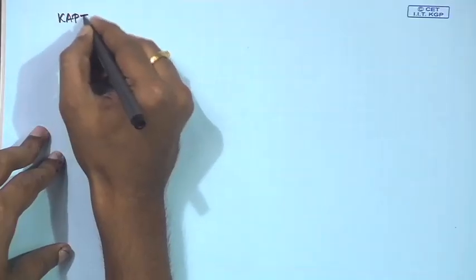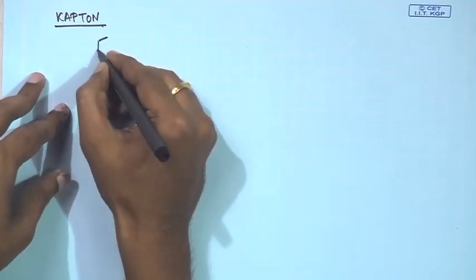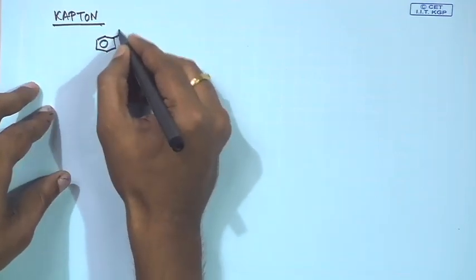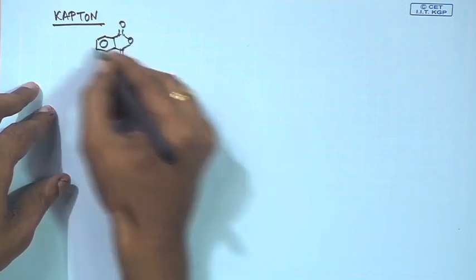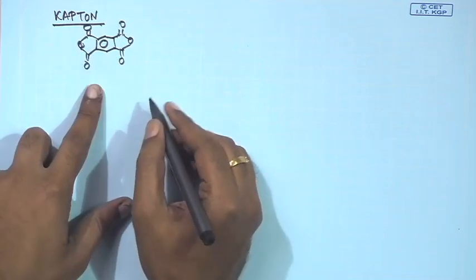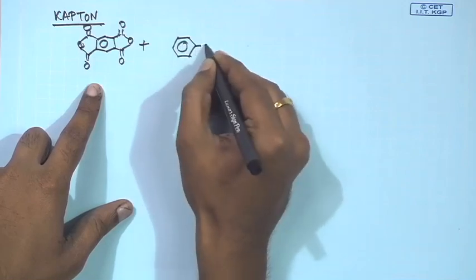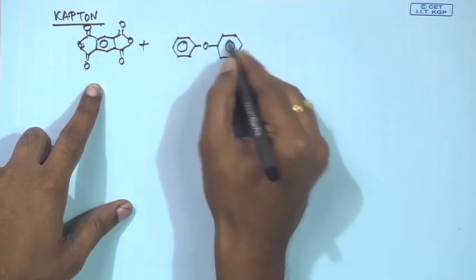So, let us continue talking more about polyimides. Let us say we will talk about one commercially important polyimide first up today. That is Kapton. So, basically if you start with your pyromellitic dianhydride, react this with a diamine which has an ether linkage, a specific diamine we are using in this case.